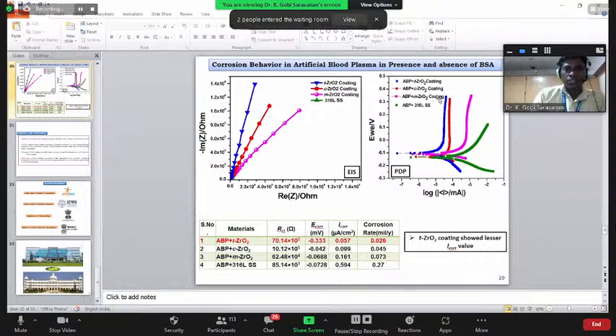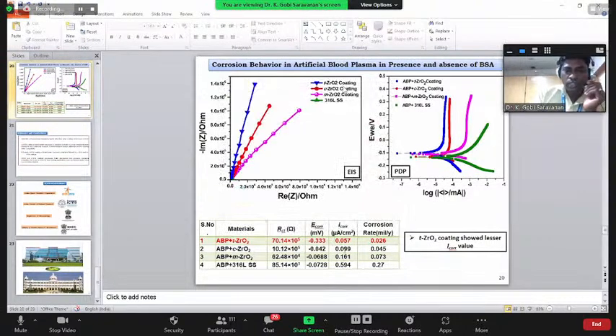Similarly, tetragonal zirconia shows higher corrosion resistance than the monoclinic, cubic as well as uncoated. Because of its higher fracture toughness. Higher fracture toughness means that this film is very smooth and very compact. Due to the compact nature of tetragonal zirconia, it possesses corrosion resistant nature, and it also reduces the corrosion current compared to the other coatings and the uncoated material.